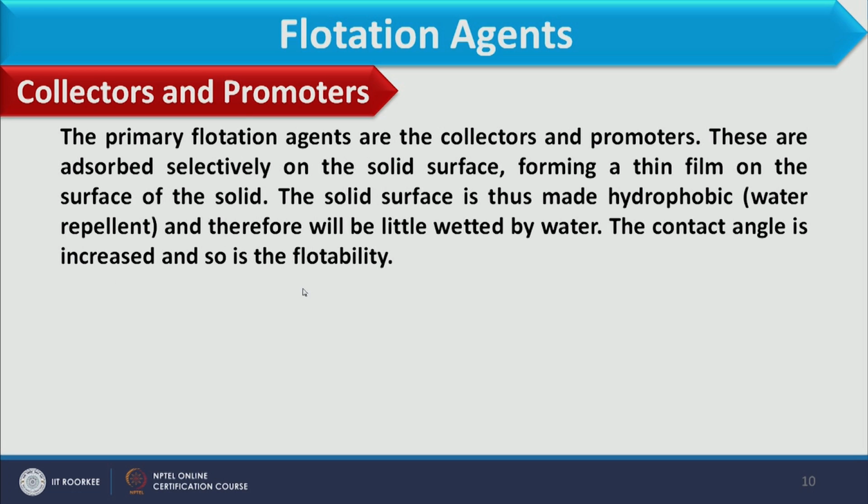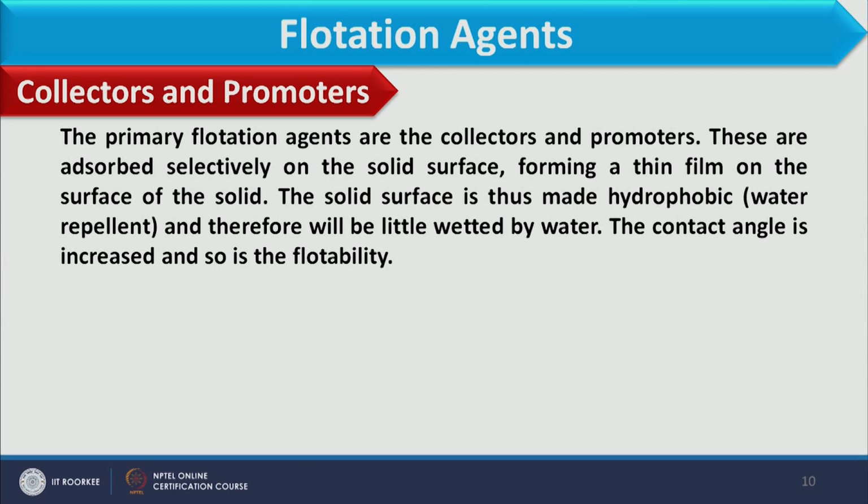Contact angle is increased, and so is the floatability. So, what is the purpose of collectors and promoters? They change the surface characteristic of a compound in such a way that it becomes water repellent, and once it becomes water repellent, it can attract air bubbles, and then the flotation will be carried out.